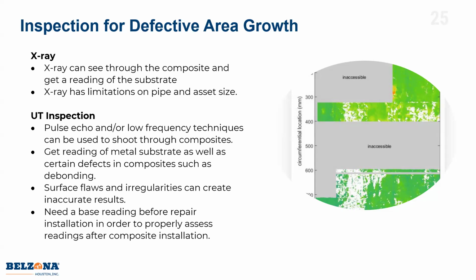We've worked with several UT inspection companies, and they've done some tests with composites, and our composites specifically. There are some things that make it tough. You want your surface to be very smooth, because normally they're using a system that's like a robot that goes around the pipe and tests it. If there's a little bump on the composite, it'll give you a false reading and tell you that you have a hole there. Sometimes the composites come out perfect. Sometimes there is a little wrinkle in there, just a resin wrinkle. So surface flaws and irregularities can create inaccurate results.